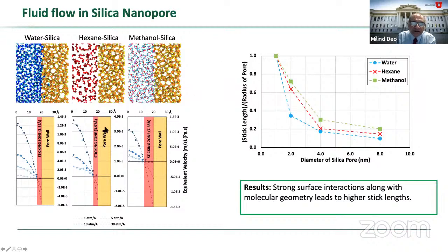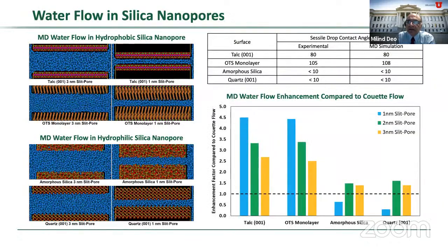And we see this happening because of what we call a sticking layer or a zone of no flow at the pore wall because of the affinity of the fluid to the silica surface. And the biggest sticking zone that we have is for methanol, and it also has the highest reduction. So instead of slip, we have a stick or negative slip, as been pointed out in the literature. So I'll provide you with some additional evidence.